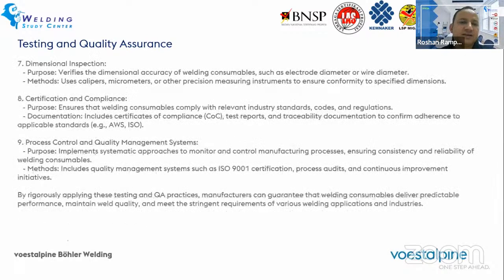Then another quality assurance criterion is the dimensional inspection of the welding consumable. So when a particular size is mentioned, like 3.2 into 350 mm for the welding electrode, there is a tolerance level given in the international standards which needs to be met for that particular size. Like it should not happen that 3.2 mm diameter is mentioned, but the actual diameter is 4 millimeter. So the selection of the welding parameters will also change accordingly. So it should be within the tolerance level.